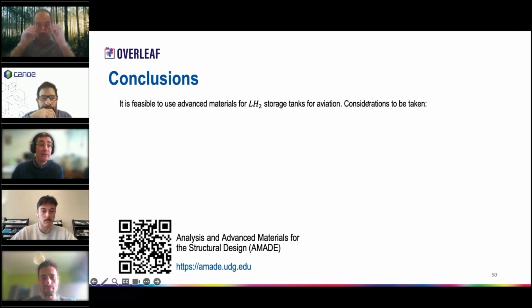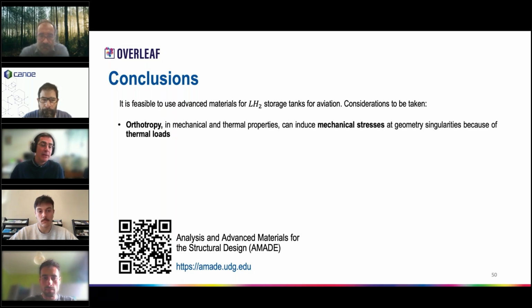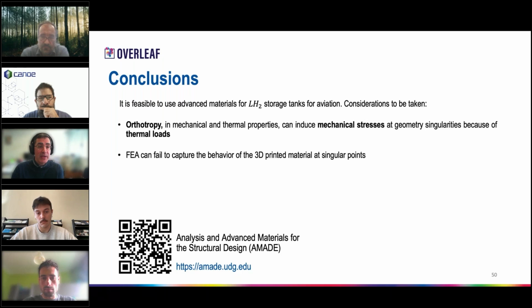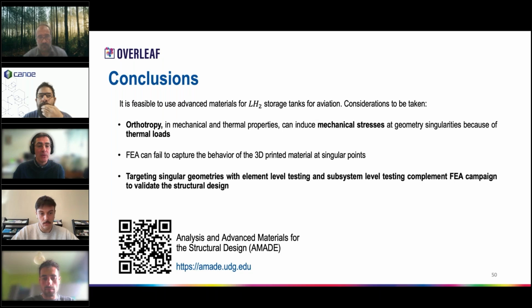Here are some conclusions that we have found so far in the project. It is feasible to use advanced materials for liquid hydrogen storage. We have seen in the previous presentations how we can create or develop them, how we can manufacture, how we can test, and how we can design with them. But in the point of testing, we have to take some considerations. The first is the orthotropy of the material that can induce mechanical stresses because of these thermal loads. So the finite element simulations, at least our simulations at this moment, are failing to capture the behavior of this 3D printed material. So we have to develop new singular geometries to try to capture these singularities.